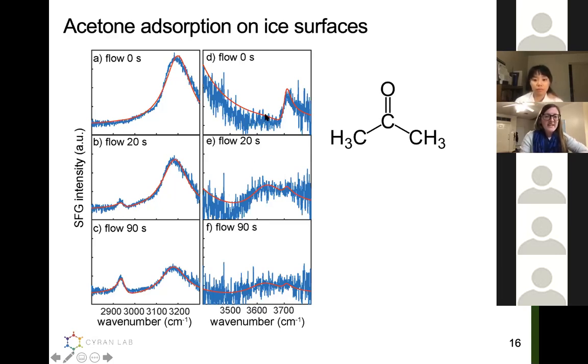What's also interesting is I looked at the free OH as well. Here you can see a bit noisier data compared to that nice spectrum I showed you at the beginning. But here is the free OH of the single crystalline ice-air interface. And then as I add acetone, we can see that this free OH is also shifting to lower frequencies. So here we start to see that we get this peak at like 3600 as well, and then the signal starts to decrease from there.